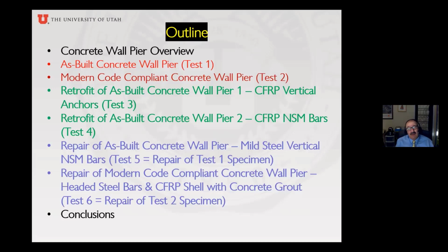And then we said, okay, now let's take the modern code compliant concrete wall pier, the one that was designed pretty recently, and let's try and repair that one. To repair that one, we used headed steel bars, a carbon fiber reinforced polymer shell, and concrete grout, or what we affectionately call around here a donut. So you see that with 4 specimens, we're actually able to do 6 tests. I'm going to describe these 6 tests to you, and I'm going to end with the conclusions.